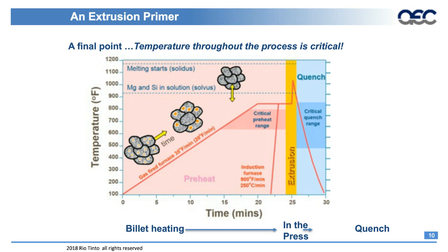But the final heating that occurs to the shape actually occurs during the extrusion process, which is obviously very much all about the frictional heat that's put into that extrusion. Now what happens during the extrusion process, obviously we're making the final shape that profile is going to be, but then we're also heating it up to the point where all of the alloying components within that aluminum alloy go into solution. So by that time, all of those alloying elements have been uniformly dispersed throughout the cross-section of the extrusion profile, and it emerges from the press. And that will be at an exit temperature somewhere between, let's say, 950 to 1,050 degrees.